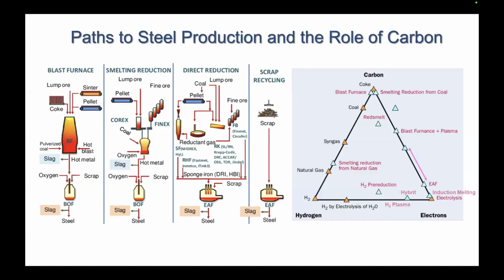So our goal here is to, of course, try to move down the carbon triangle and utilize EAF processing and hydrogen DRI production to produce a low carbon footprint steel. The path here is a variant of a scrap feed path where we use scrap to feed the electric furnace, which is also a low emission route. And we utilize the virgin iron units to offset the accumulation of tramp element residuals in the scrap.